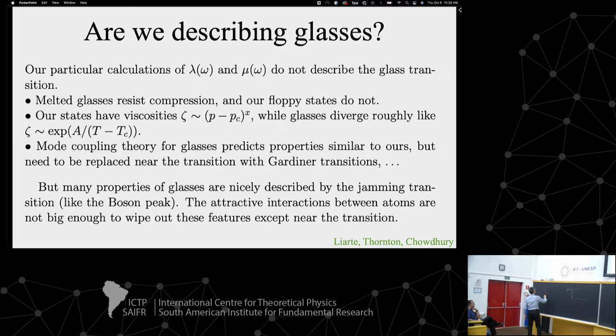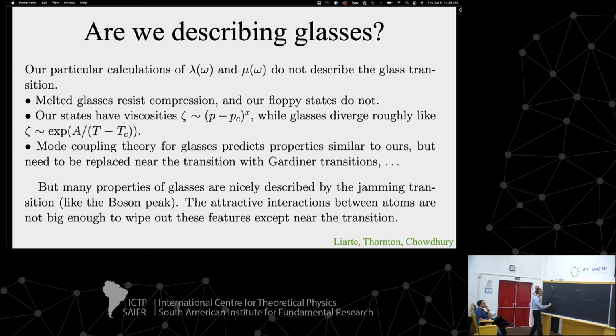And then I have to explain what the Boson peak is, and this is going to be a little obscure. If you plot the specific heat as a function of temperature, on a log plot, it looks linear at first. Then there's a region which looks linear, and there's a region that looks cubic. So this is T, and this is T cubed, while the crystal just looks like T cubed. Crystal looks like T cubed, and a glass always has this T.